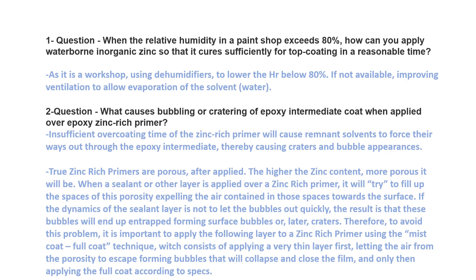Between the zinc porosity there would be some trapped air. If that air wants to be released when applying the sealant or intermediate coat, it will come through the intermediate coat and form bubbles or craters.